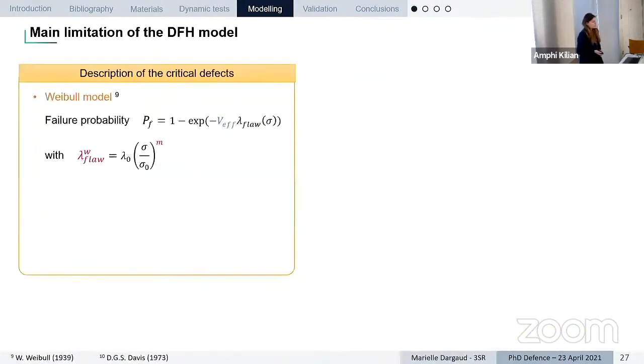So the current DFH model is actually using specific data to describe the critical density of defects. Currently, we use the DFH model, the Weibull model, sorry, which says that we have a probability of failure in the material, which is related to the flaw population that you have right here. And this flaw population in this Weibull model is expressed according to the principal stress, sigma, and the Weibull modulus, m.